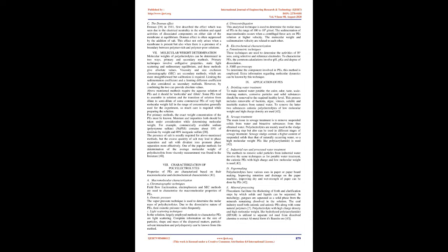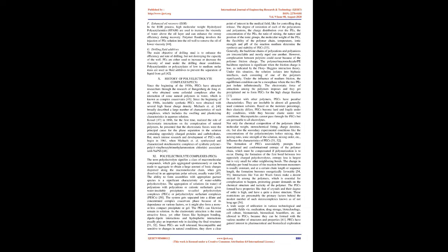Ions formed by dissociation of PEs are not evenly distributed in the solution but remain in the neighborhood of polyion, creating an ionic environment. Many researchers have agreed on the approach of the Debye-Huckel theory of simple electrolytes, and some used the Poisson-Boltzmann equation to determine the electrostatic potential around the polyions. While some researchers consider polyion as a charged cylinder or worm-like chain and reported that above critical charge density, the counter ions condense. For uncondensed counter ions, the Debye-Huckel theory is used. The most recent approach is the hypernetted chain integral equation in computer simulation method 38.